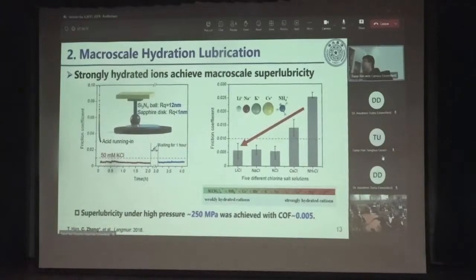Then we did the test with a ball on disc tribometer, and the ball is here a silicon nitride ball, and the disc is a sapphire disc. At the beginning, we run the test with acid solution. We can find the friction coefficient decreases rapidly. After the running-in period, we removed the acid solution and used potassium chloride solution as the lubricant. And then we find the super low friction coefficient of 0.005 was obtained. And here the contact pressure is about 250 megapascal, a very large contact pressure.